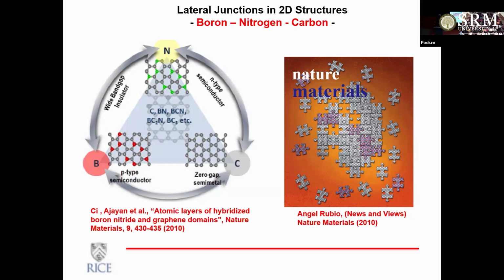There are carbon nitrides, which are catalytically very interesting for nitrogen-doped carbons, right? So those are fascinating. They also exist in hexagonal and cubic form. And then there are also the three-component systems, the boron, carbon, nitrogen systems. There are compositions like BCN, there are compositions like BC2N, BC3. There are many, many compositions, right? And some of them are semiconductors, some of them are metallic, and they are all single atom thick. If you think about it, the truly single atom thick material is essentially graphene or boron nitride, right? The molybdenum sulfides and others have slightly thicker unit thickness.